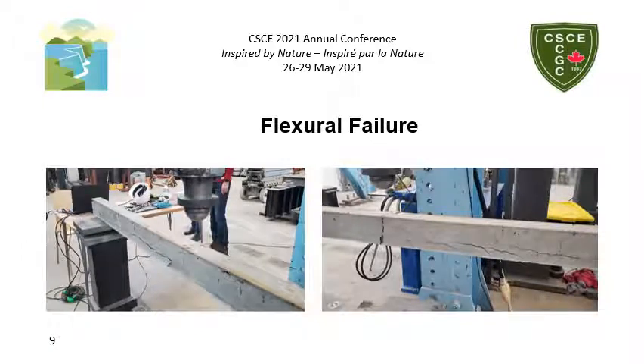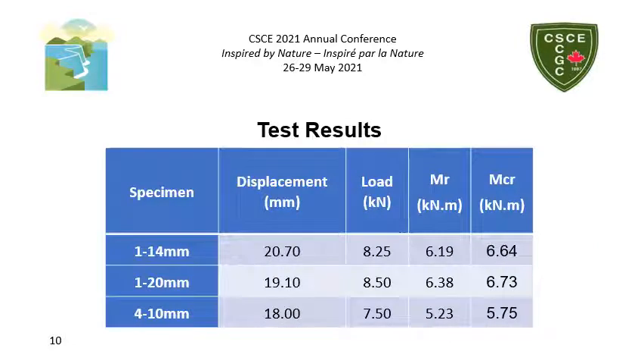The crack pattern and failure mode were similar in the different specimens that had various rebar configurations. In all cases, the failure is due to the concrete reaching ultimate strength and not due to rebar ultimate strength. The test results are summarized in this table.